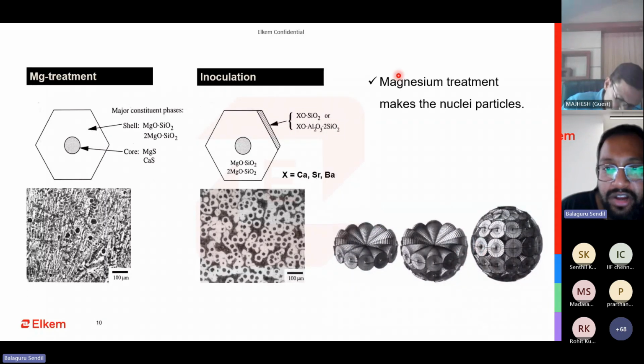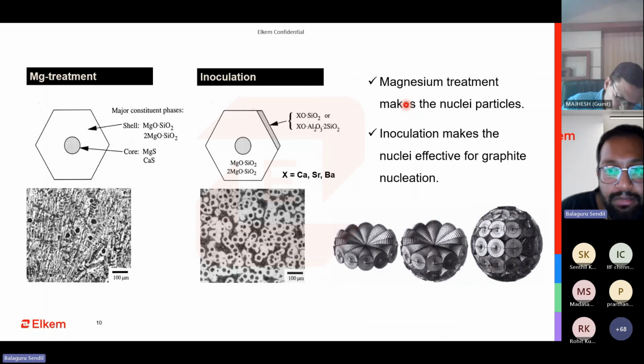What happens? Magnesium treatment makes the nuclei particle, inoculant makes the nuclei effective for graphite nucleation. That is the growth of the graphite. So that is why when you're doing magnesium treatment, you see a lot of these sites, but these sites are quite small. The graphite has not come and settled down there. A subsequent inoculation, the correct inoculation, will make sure that you have very nice carbon growing in the correct shape and size to have a very perfect nodule.